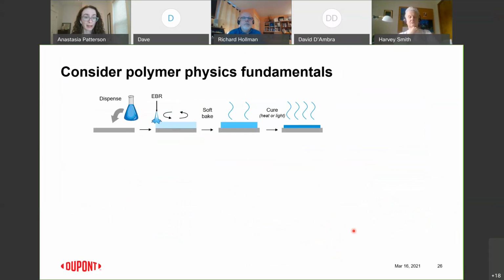So we took a step back and looked at the actual coating process and asked, where does this actually happen in the film creation process? So this is a spin-coated material. It's dispensed on a silicon wafer. It's spun to set the film thickness, and the edges are rinsed off with this edge bead removal solvent. It's then soft baked to remove much of the solvent and then cured. In this case, it's with heat, but it could be with a lot of different stimuli, like light.